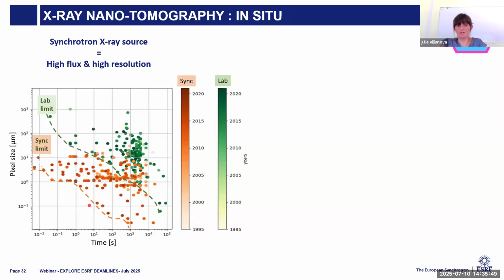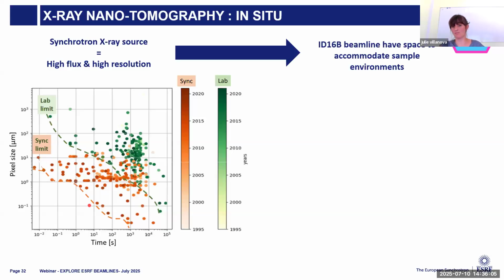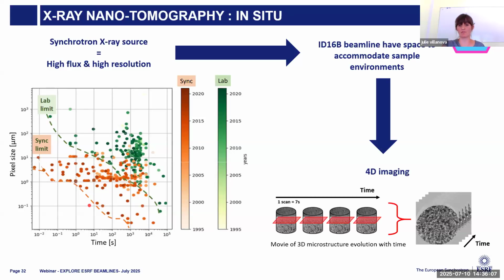So tomography is a non-destructive technique. The synchrotron X-ray source allows us to have high flux and high resolution. So it means, and it's what is shown here in this graph, that we are able to perform tomography with small pixel size and fast acquisition time. And since at the beamline we have space to accommodate sample environments, we can perform 4D imaging. It just means that you will perform tomography one after the other in order to be able to reconstruct 3D as a function of time, and then end up with a 3D movie of the evolution of the microstructure of your sample.